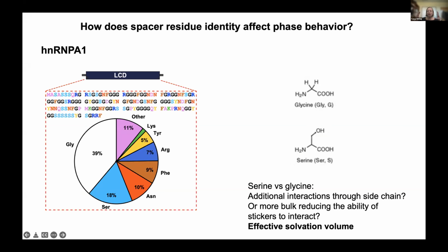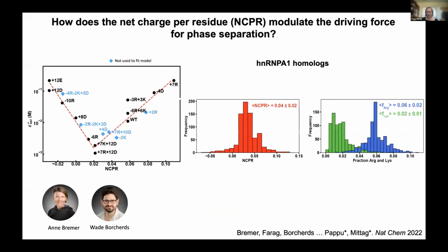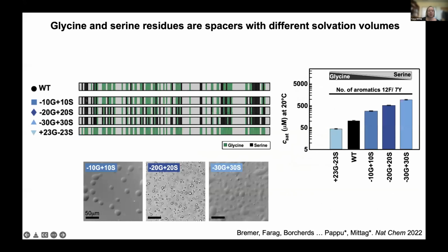I think Rohit mentioned it. We're thinking about how much volume the side chain takes up, either by its normal bulk or by how much it likes to be solvated and therefore expands the chain. So which of these properties is more important for the phase behavior of these sequences? To answer this, Anne and Wade in my lab made a number of variants where they replaced increasing numbers of glycines with serines, and this weakened phase separation. And when they replaced all serine residues with glycines, this strengthened phase separation, really arguing that serine is indeed a spacer, not a weak sticker, and glycine is the more favorable spacer of the two.